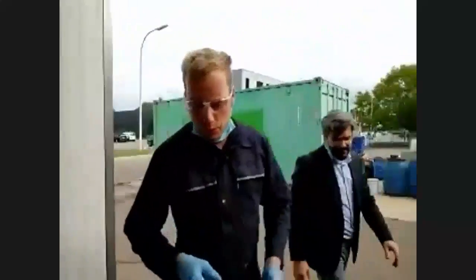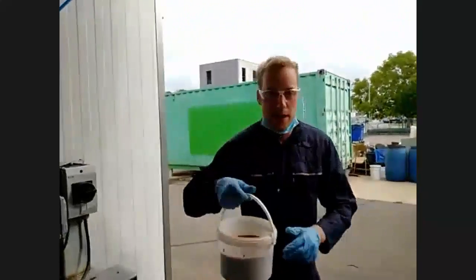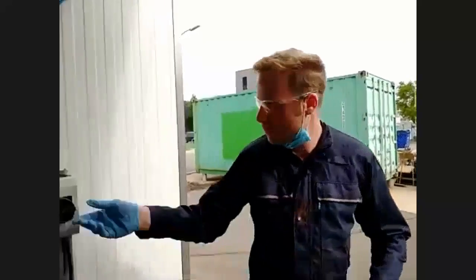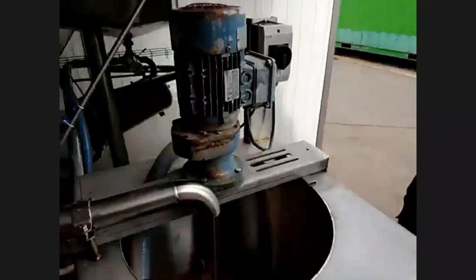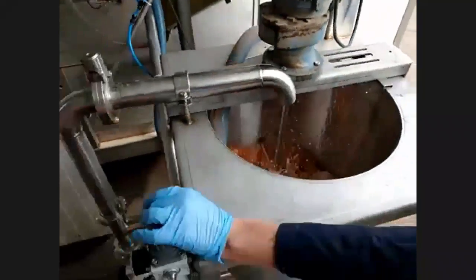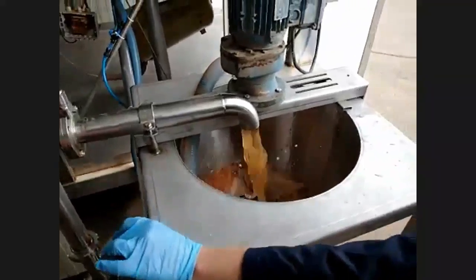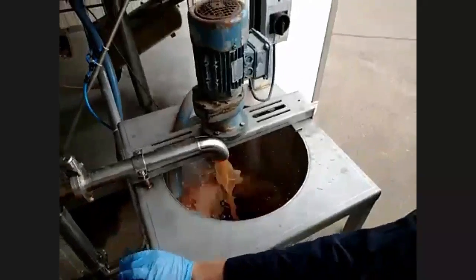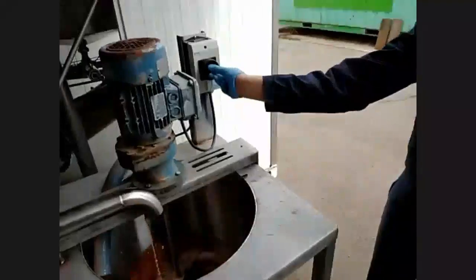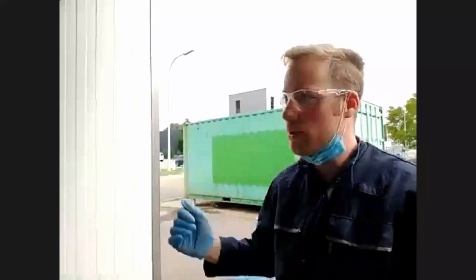So, what we do first is put this material inside the mixer, and we can put additives inside, make it even more liquid, less liquid, and then we can run through the container. So I will show you how we mix the red mud, how we add the additives, and how it is pumped through. So now we have seen where we bring in the red mud, we mix with the additives, and then it will go to a bigger tank. And that I will show you in this beautiful container.